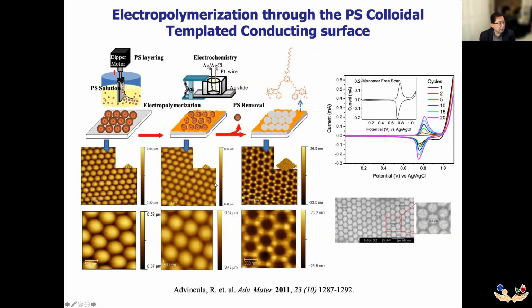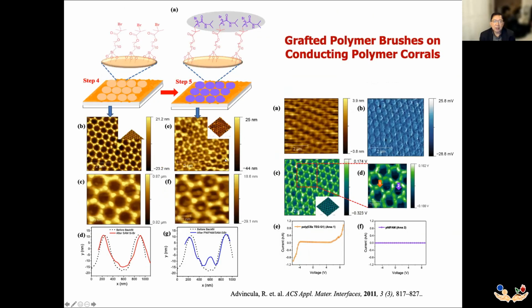Now, these patterns are arrays of conducting polymers with holes in the middle. The holes in the middle basically expose the substrate, and as you can see from the AFM and SEM pictures, we have a regular array of this conducting polymer. On the other hand, in the middle of this, which exposes the electrode surface, we can then grow an ATRP initiator, and then finally a polyNIPAM brush, which, as shown here, backfills or fills the array.